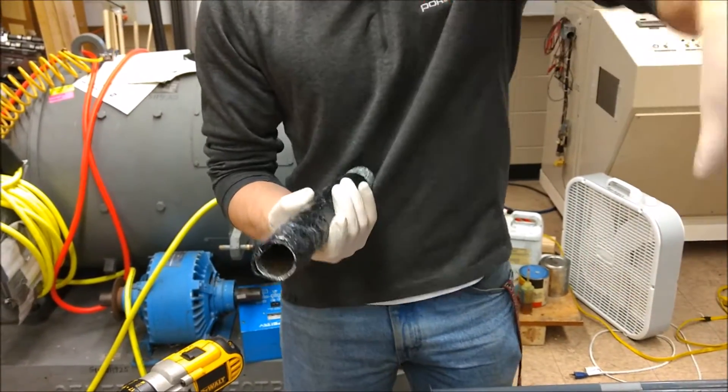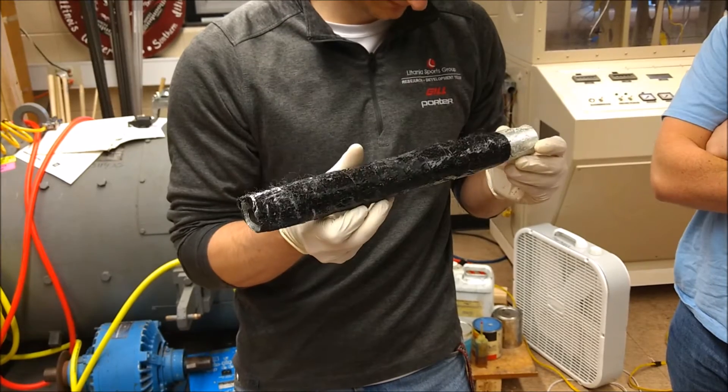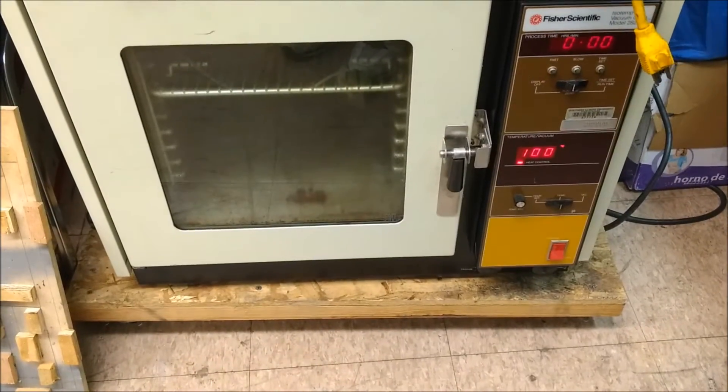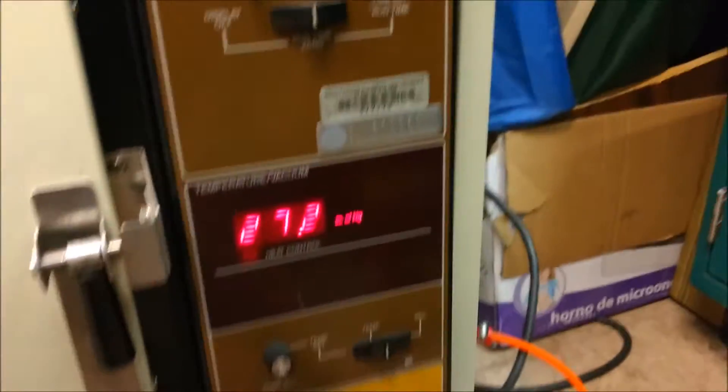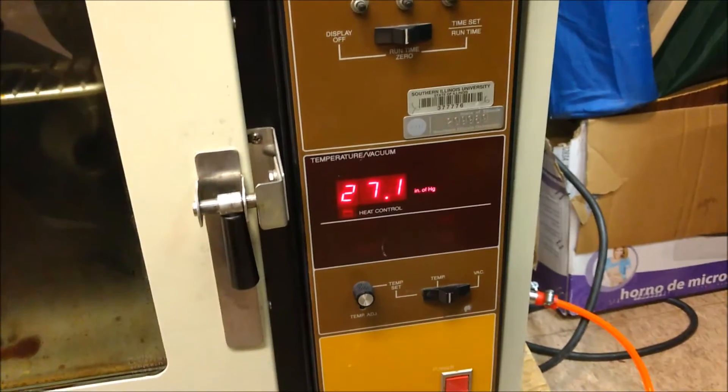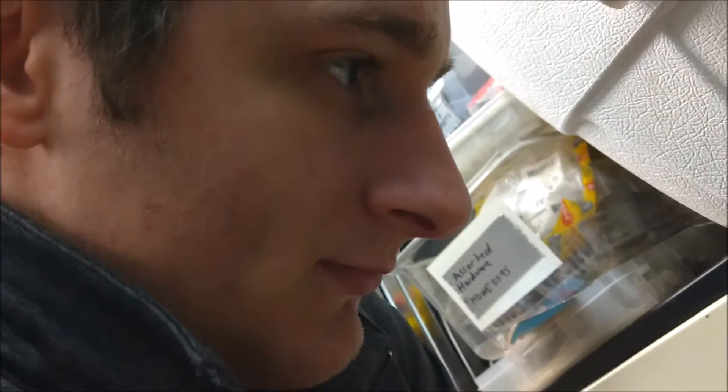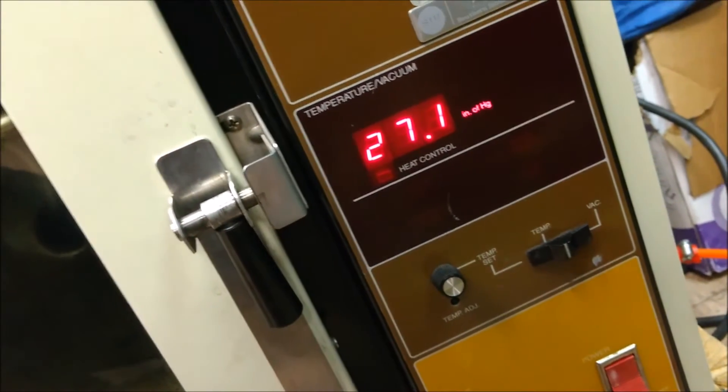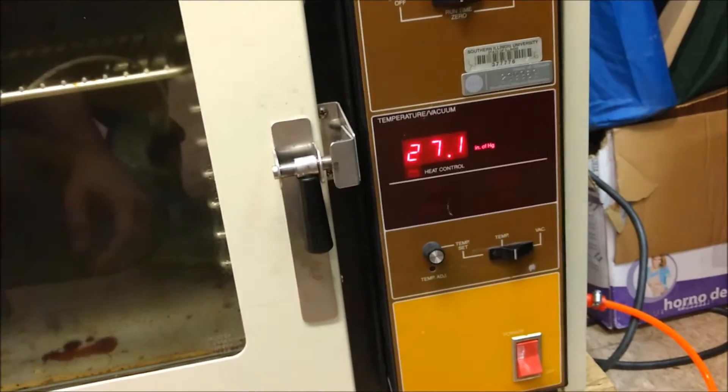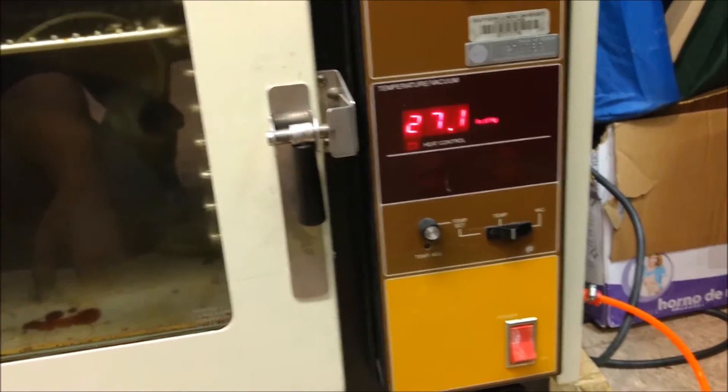Are you worried? Yeah. It really doesn't look like it did much. Stupid scotch tape. Is it still sticky? What do you think? Yes. Yeah, so we need to do a post-cure. Fire up the oven. 120 Celsius for one hour because this is still viable. So we're finally plugging the vacuum because we have this valve open. Good job. It's slowly pulling it. Our carbon fiber started curing so I wasn't very happy about that.